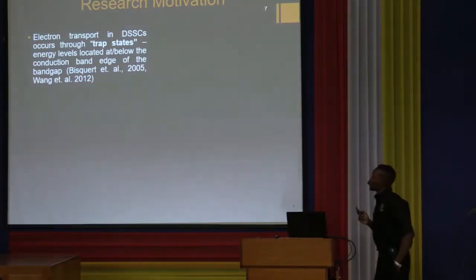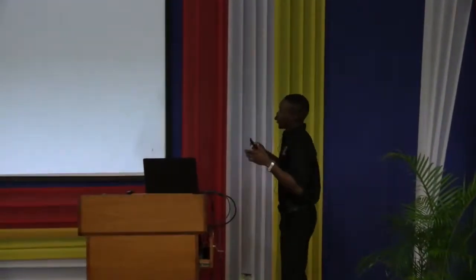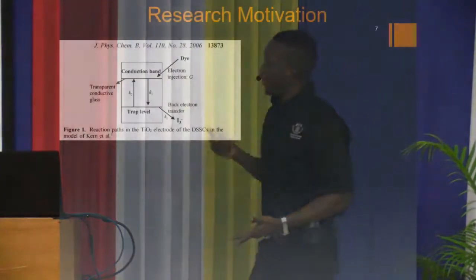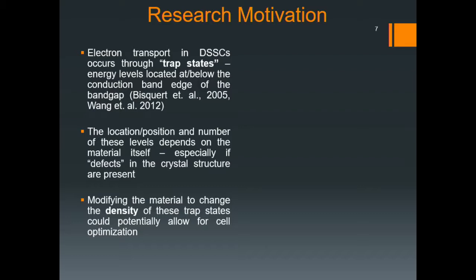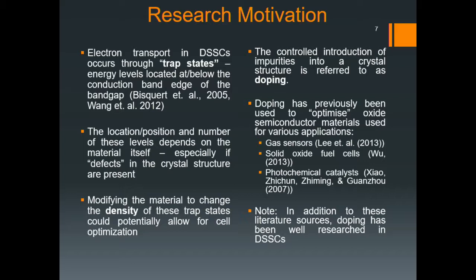What we know about dye-sensitized solar cells is that electron transport occurs through trap states, which are energy levels located in or close to the band gap of the material. So in the material structure, there are states referred to as trap states that electrons can travel between as they move throughout the cell. It has been shown that electron transport takes place through those trap states, and the location and position of the trap states can be modified by changing the properties of the material. So by doping, by introducing external impurity elements, we can modify the behavior and the electrochemical characteristics of our cells by modifying the trap state density.